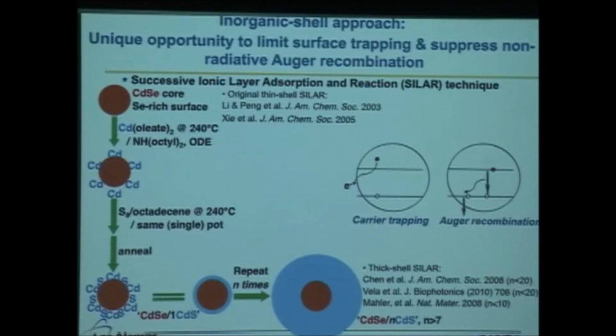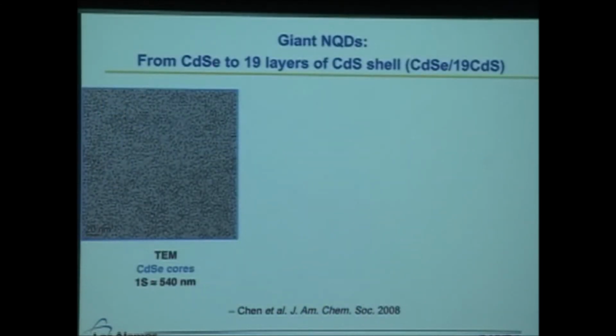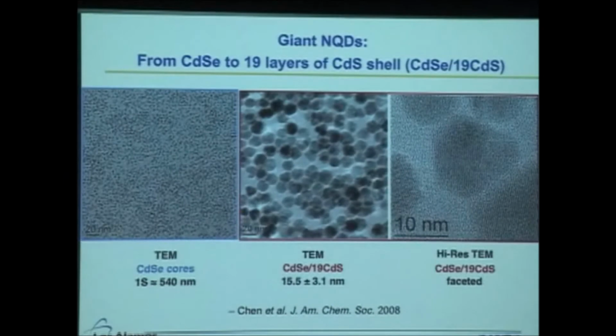Our systems tend to focus on shells that are very, very thick, up to about 20 monolayers of shell material. In this case, cadmium sulfide deposited on the cadmium selenide gives us that quasi-type 2 electronic structure. And just as a visual for why we call these things giant, we're typically used to working with quantum dots in this size range, 3 to 4 nanometers, shown here on the same scale. After we grow, say, 19 monolayers of shell, our particles are between 12 and 20 nanometers, depending on how many shells we grow. In some sense they're giant, but that wasn't meant to scare away the biologists who like to have things small. I think they're still small enough for practical use in many single molecule applications. The high-res image on the right shows the nice crystallinity and the faceting that we achieve, which reflects the underlying hexagonal crystal structure of the system.